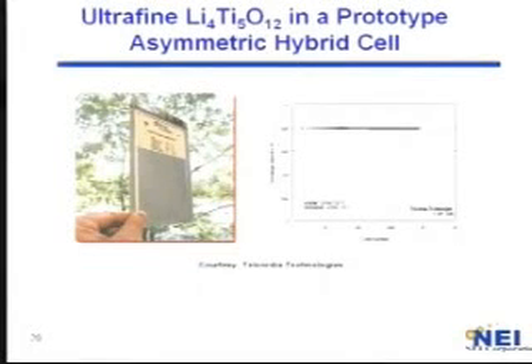This is just showing a prototype device using this material, an asymmetric device. And this is just to show the cyclability. It has been cycled for more than 10,000 cycles, and it does not show any degradation in the capacity.